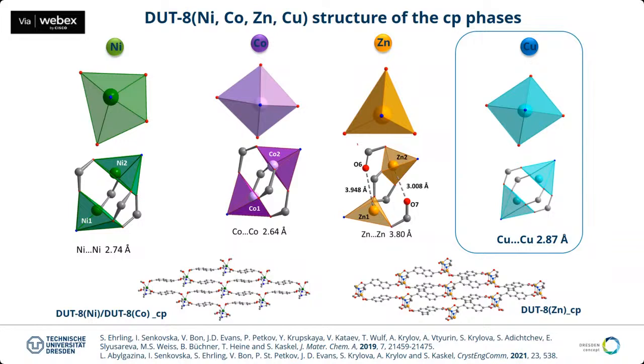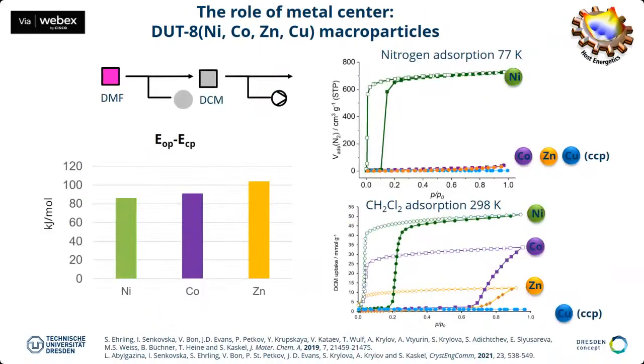So in the contracted structure of the zinc variant, you can make all the DUT-8 structures with nickel, cobalt, zinc, and copper. In the zinc structure, you almost go from, let's say, a square pyramidal coordination to a more tetrahedral type of coordination, and also the distance between the zinc atoms is very much changed. So this already tells you that the node here is the flexible unit. The zinc cluster is very flexible. It's a soft node, while the nickel cluster is more a hard node. It's more difficult to transform. I will not talk about the copper structure because it's a bit more complicated. It's different.